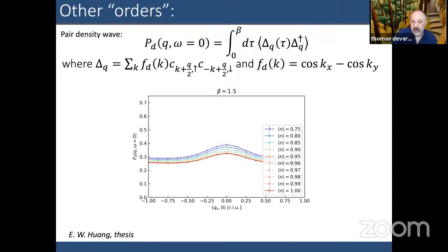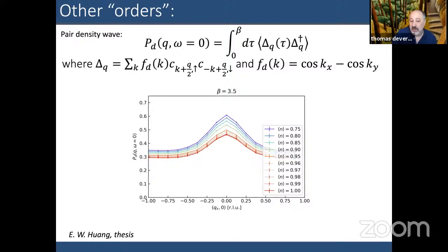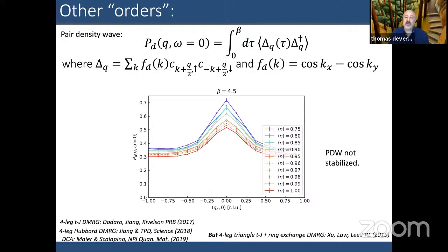And as one cools down, you see that the peak intensity grows, but there's no signature of anything happening out at any other momentum point, meaning Q equal to zero seems to be the most dominant contribution to the pair field susceptibility. Of course, we're limited by the resolution of the cluster size that we can look at, and I can't say anything of what may happen at lower temperatures, but at least on the temperature scales in which we can see fluctuating stripes and an increase in superconducting order, there's no sign of anything happening out at finite Q.